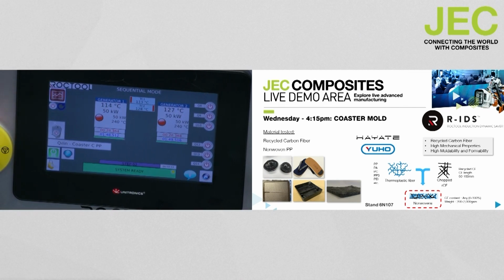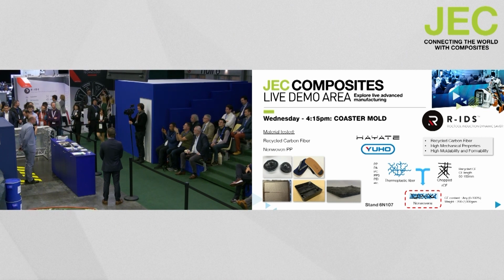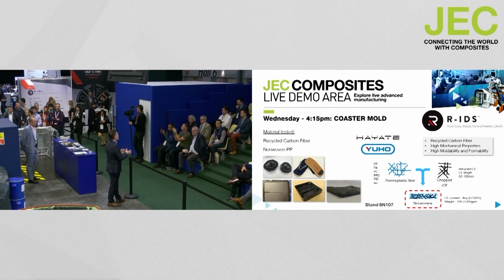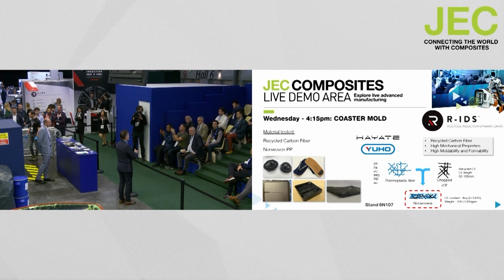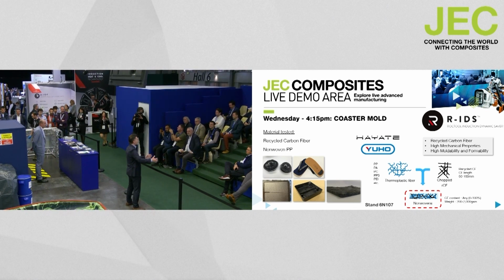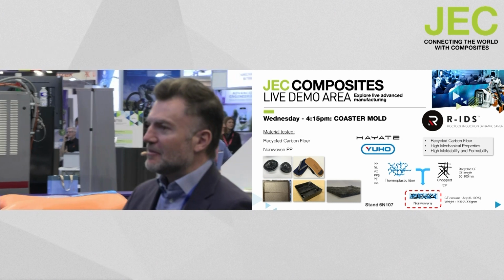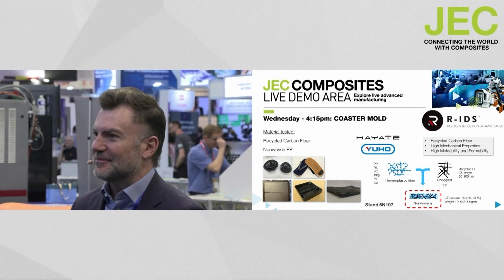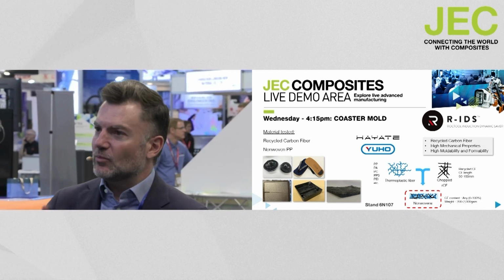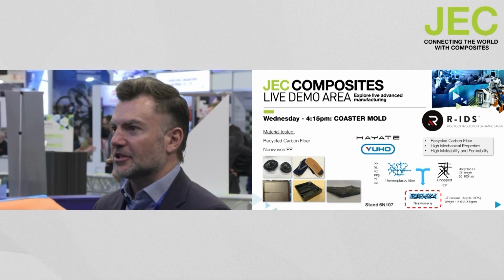So you see also that because we use thermoplastic composite material, we start to reduce the cycle time, and we use for this application 50 kilowatts per side to be able to reach the maximum temperature in a short time. So here for the show, we're doing one part, and then later another one, and then later another one. So it's not really a manufacturing environment. We're doing a demonstration. But let's look at what we would do if we were in production, right?